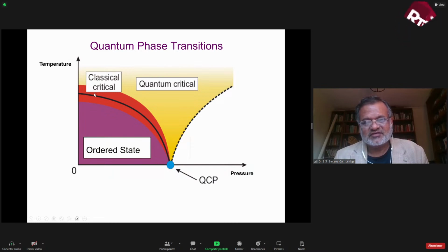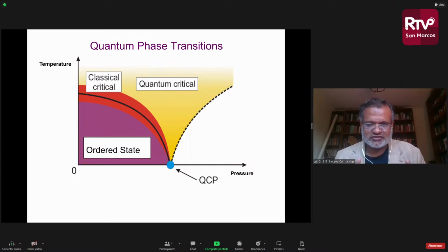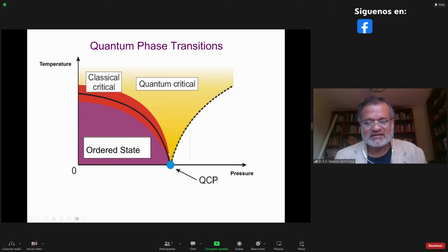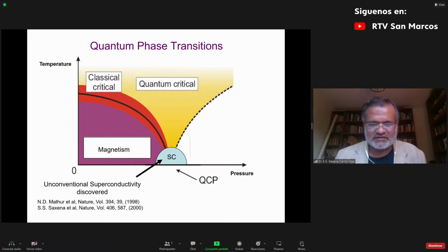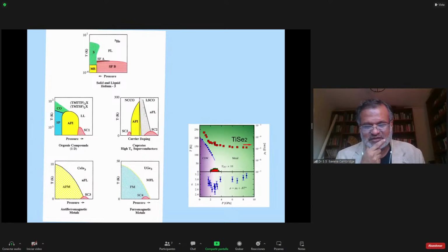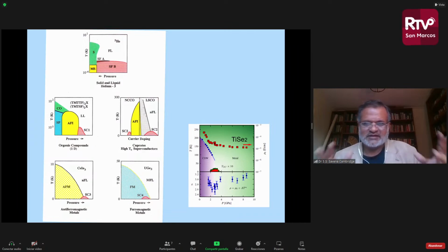You can play this game until you suppress this ordered state, in our case the magnetic one, and then all the entropy gets squashed into that corner of the phase diagram, what we call a quantum critical point or quantum phase transition. Many states become equal in energy and can pop out in this region, and the most famous of them is the superconductivity that emerges here. Pursuit of this work has led us to quite a new set of things, which I will share with you. This kind of phenomenon is not only in the materials that I have measured, but it broadly happens as almost a universality class.